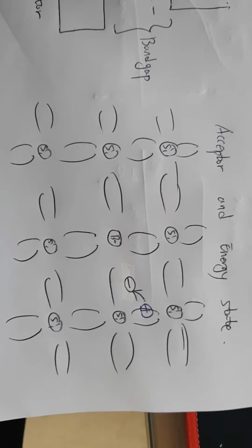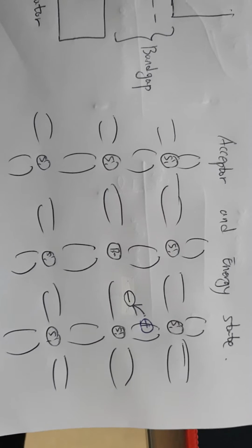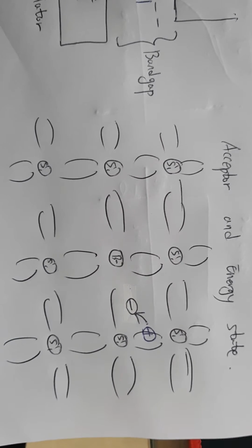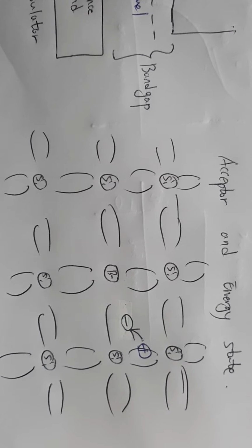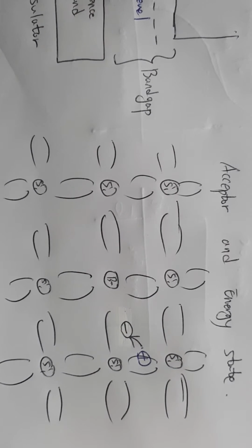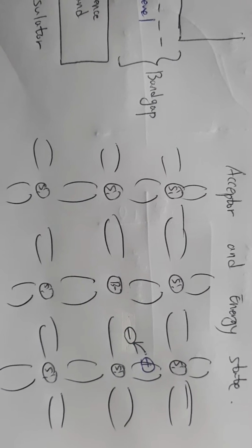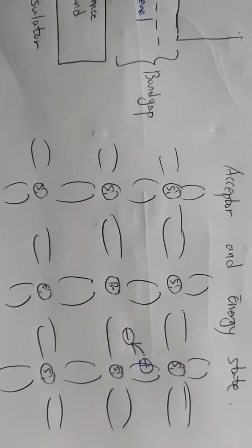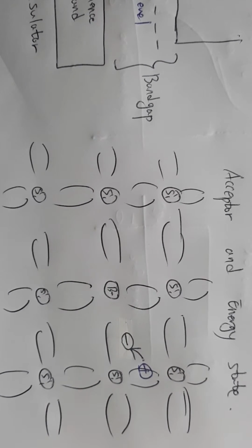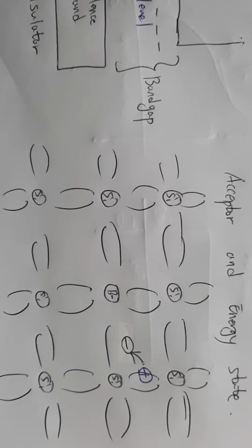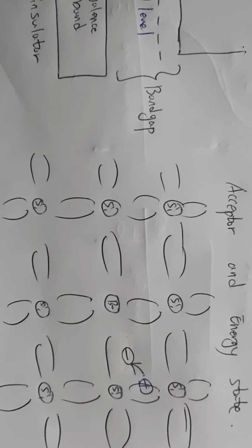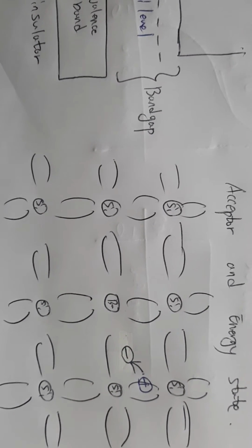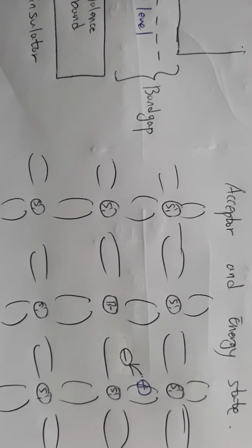An acceptor is a dopant atom that, when added to a semiconductor, can form a p-type region. When substituting for a silicon atom in the crystal lattice, the 3 valence electrons of boron form covalent bonds with 3 of the silicon neighbors, but the bond with the fourth neighbor remains unsatisfied. The unsatisfied bond attracts electrons from the neighboring bond. At room temperature, an electron from a neighboring bond will jump to repair the unsatisfied bond, thus leaving a hole. Thus, the initially electroneutral acceptor becomes negatively charged.